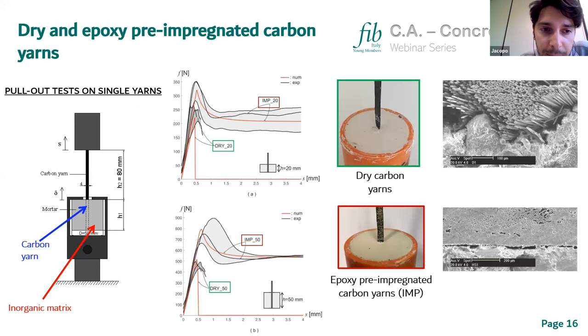Here I show you some experimental tests that we carried out at our university on dry and epoxy pre-impregnated carbon yarns. We performed this pull-out test on single yarns, and you can see the very different behavior of dry and coated yarn. In the case of dry yarns, we have an elastic behavior up to failure, which is brittle, with the failure of the external filaments of the yarn. While in the case of coated, pre-impregnated carbon yarns, we have a higher peak load, and then the detachment of the yarn from the mortar. But in this case, we have a very high friction between the external surface of the coating and the mortar.